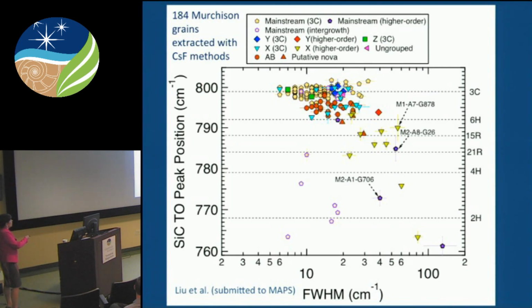And in fact, right here, in a collaboration between DTM and GL and the Naval Research Lab, over 184 of these grains were measured by Nan Lu, who's a postdoc in DTM, using Andrew Steele's WITec Raman system, to determine what the polytype distribution was. And she found that, again, the vast majority, roughly 80% of them, were indeed consistent with the 3C crystal structure.